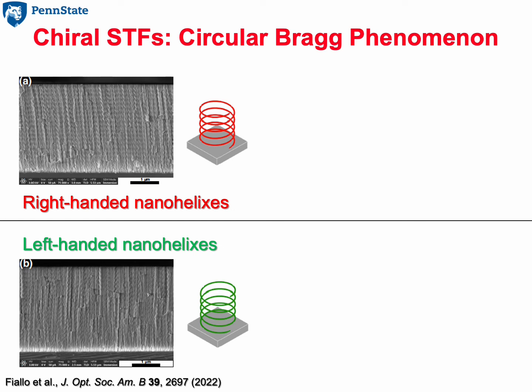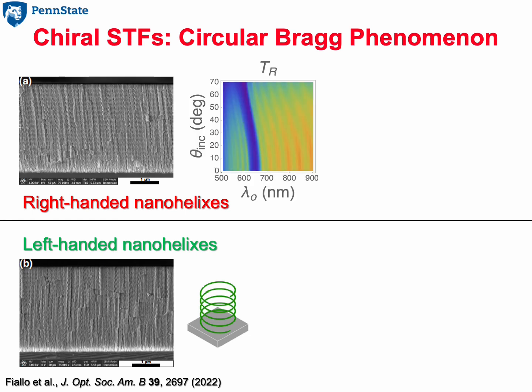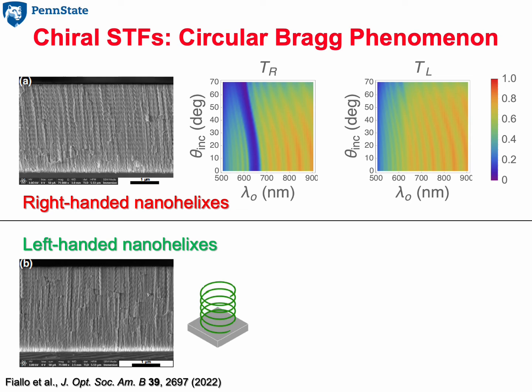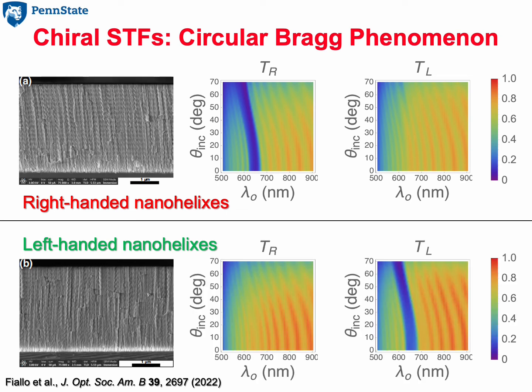This polarization state dependent phenomenon is called the circular Bragg phenomenon, and it occurs in a specific spectral regime. Here you see a blue band in the transmittance spectrum of incident right circularly polarized light. The chiral STF is structurally right-handed. The blue band is absent in the transmittance spectrum of incident left circularly polarized light. So the structurally right-handed chiral STF can be used as a band stop filter for right circularly polarized light. The blue band switches if the nanohelices are left-handed. Hence, the structurally left-handed chiral sculptured thin film can be used as a band stop filter for left circularly polarized light.